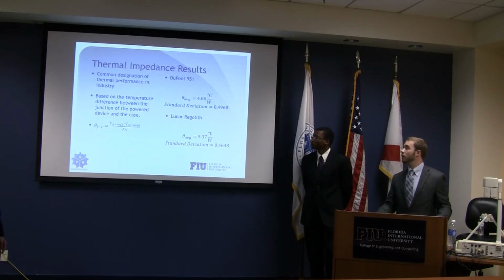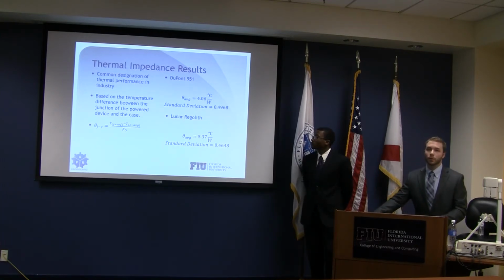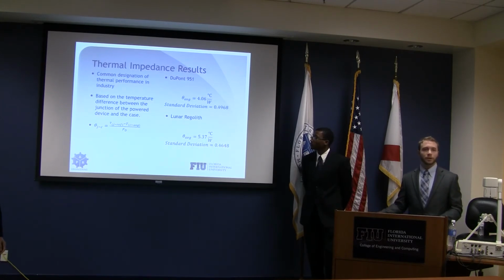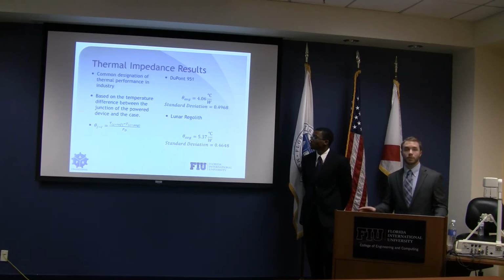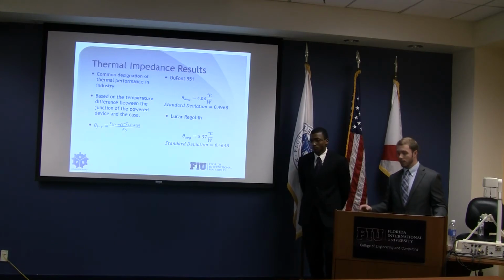So with that being said, we found the DuPont 951 produced a thermal impedance of 4.06 degrees Celsius per watt with a standard deviation of about 0.5. The regolith had a slightly higher thermal impedance, which was 5.37 degrees Celsius per watt, with a lower standard deviation of 0.4648.